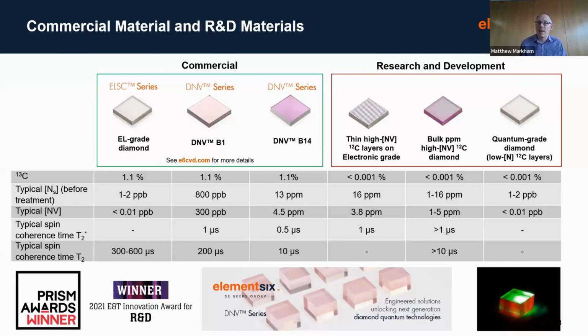I've mentioned mostly the nitrogen vacancy defect, but there are other interesting defects, and people use our electronic grade diamond to implant different elements into it and create other defects. And then we've got what we call the DNV series, which is basically addressing sensing type applications where you want a higher NV content material. We have two different grades here, a B1 grade and B14, where effectively the number relates to the nitrogen concentration in the material. The reason we have two different grades is, as I said earlier, the material of choice depends on your device design. Some device designs B1 will be better, and for some a B14 would be better.